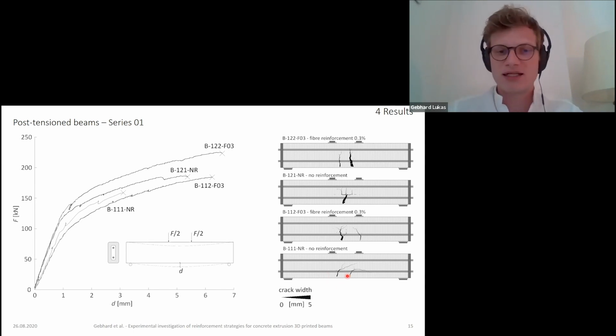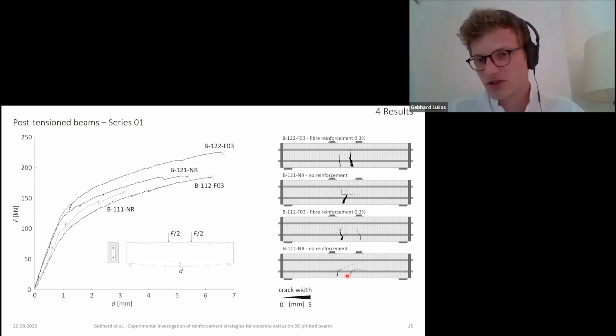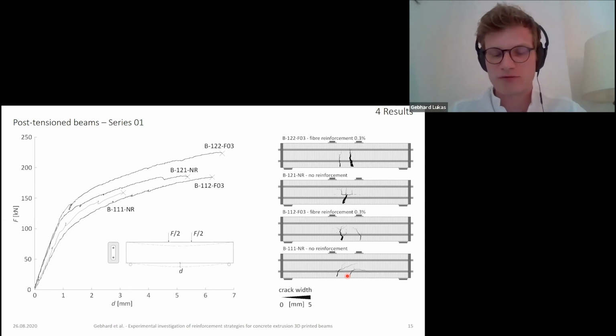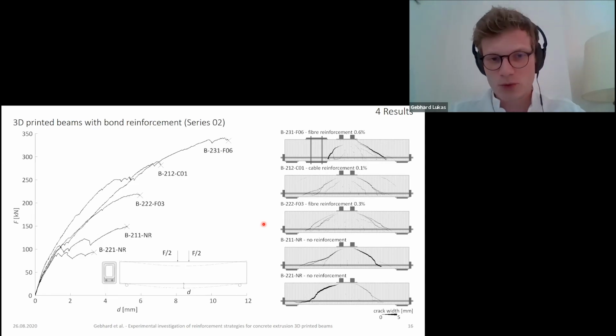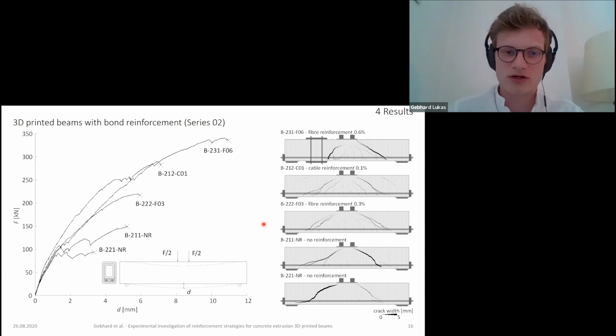This was mainly caused by some torsion we had in the system, because for the first beam we did not have sufficient out-of-plane stabilization for the beams. What we could also see was that all the beams failed brittly at their ultimate load, and the ultimate load could be increased in both cases when fibers were present. However, since we only developed these bending cracks and no shear cracks, the fibers could not really be activated as shear reinforcement.